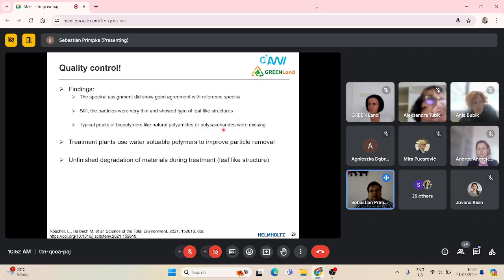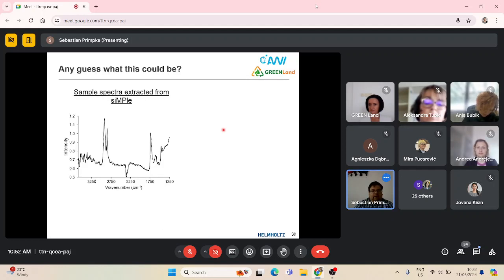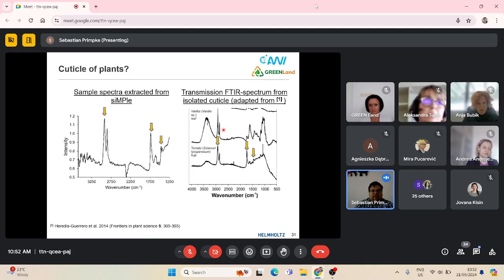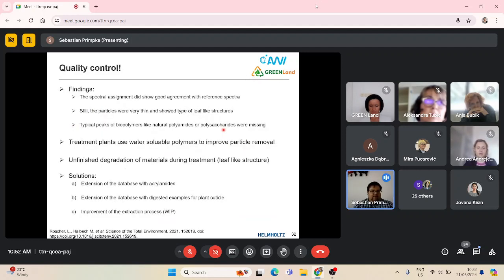We thought that could be a source, but we also checked what type of plant residues could resist our degradation process. So we checked the literature again, and found that plant cuticles can yield a spectrum quite close to polyesters, polyurethanes, acrylates, and so on. Then we did our digestion process on it as well and figured out that we had just used the perfect isolation process for plant cuticles. So we added it to our database, as we added polyacrylamides. We're still working on how to remove them best, as we haven't had any sample with the same issues since.